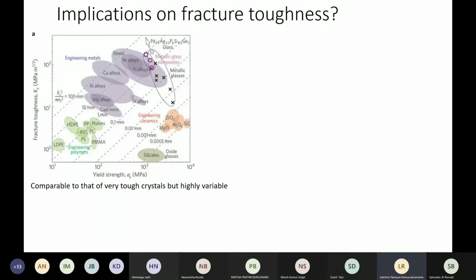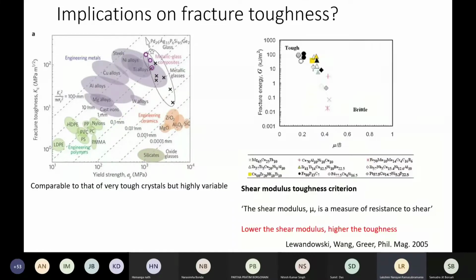But if you notice one thing, metallic glasses also have a very high range of toughness. It can be as low as 10 MPa root meter, but also can be as high as 100 MPa root meter. As you can see, the y-axis here is a logarithmic axis, and hence from 10 to 100, the toughness of your metallic glass can vary. So this high level of variability brings in the question: what factors decide the toughness of metallic glasses? What is the inherent physical or mechanical property that controls your metallic glass fracture toughness?